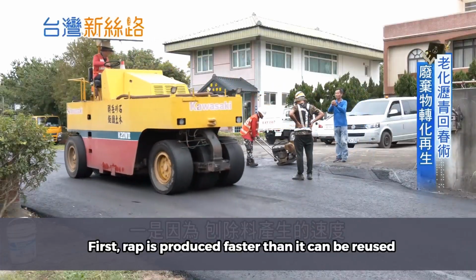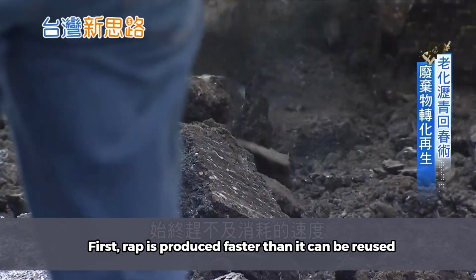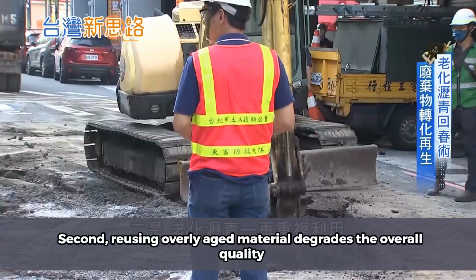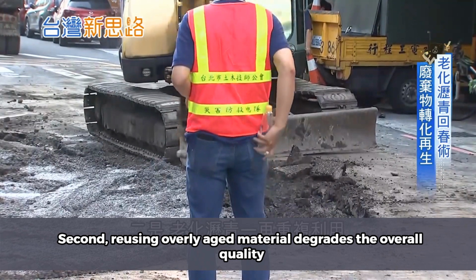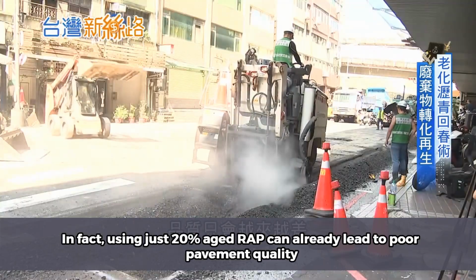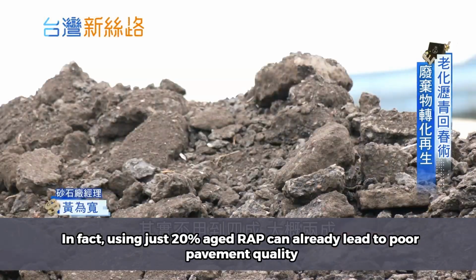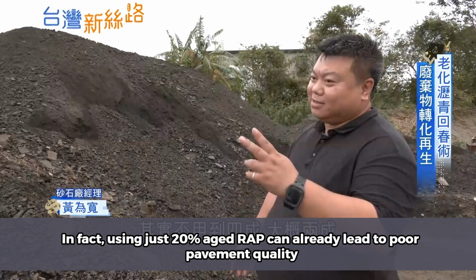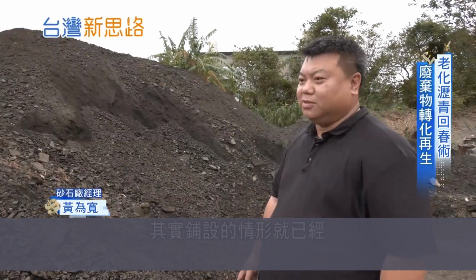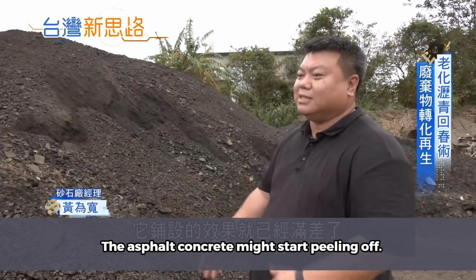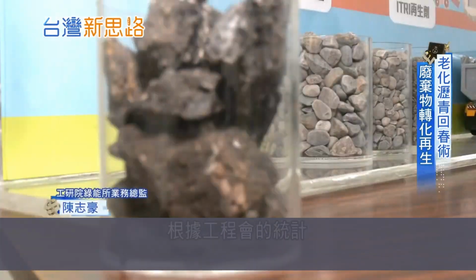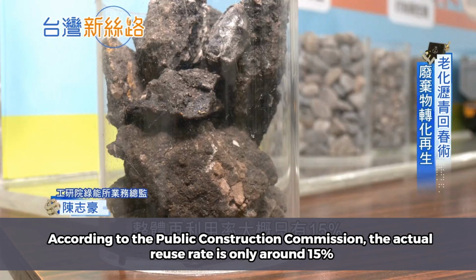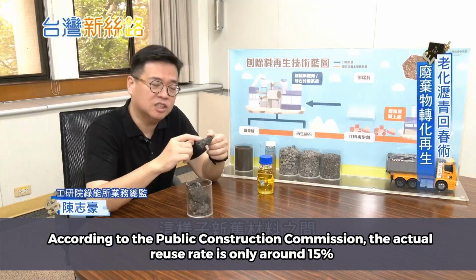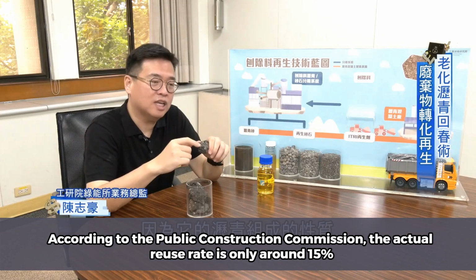First, RAP is produced faster than it can be reused. Second, reusing overly aged material degrades the overall quality. In fact, using just 20% aged RAP can already lead to poor pavement quality. The asphalt concrete might start peeling off. According to the Public Construction Commission, the actual reuse rate is only around 15%.